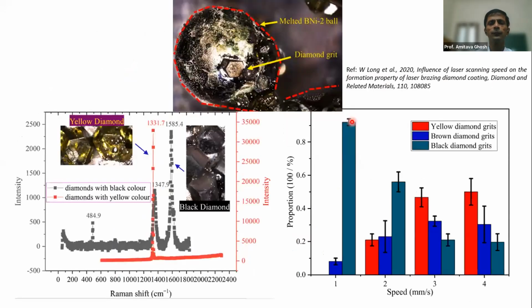There is a difference in the color the group has observed. If you have a very low speed of scanning, there is a change in the color. This change in the color is nothing but because of graphitization, the order of graphitization of the diamond. So if it is very fast, then graphitization takes place very little. So the black diamond grades would be much lower in percentage.